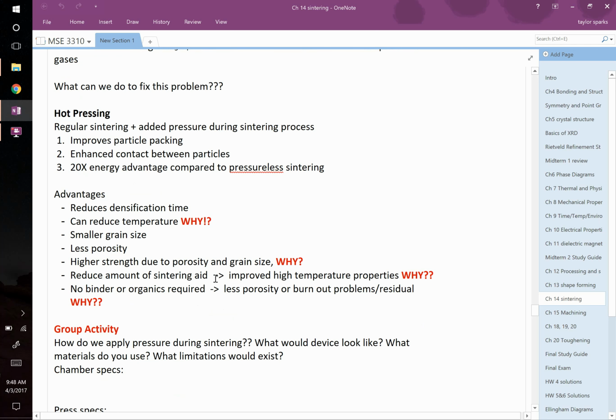So here are some advantages. You reduce your densification time because once you get it to the point where it's softening and you've got transport, by adding that extra pressure, your transport mechanisms just really take off. You can reduce temperature. Any thoughts on why you'd be able to reduce temperature? Sure, right? Temperature is basically giving you time and temperature. So you could do it for longer times at this lower temperature, or you go to higher temperatures for shorter times, right? You get smaller grain size because you're holding it for less time.